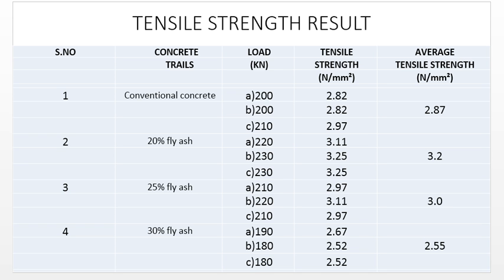By conducting the tensile strength test for cylinder, we get the average tensile strength. At 20% fly ash replaced by weight of cement, it gives the maximum tensile strength, that is 3.2 Newton per mm square. Beyond that, the strength is going to decrease when compared to conventional concrete. The 20% replaced fly ash gives more tensile strength.